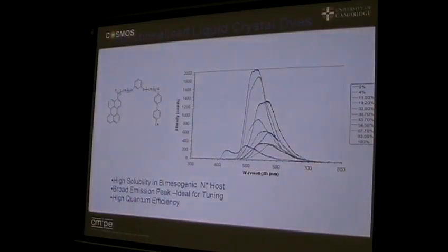One of the ways in which we improve these systems and improve the dyes is, as I said at the very beginning, that you need a high order parameter in the dye. Just to give you a feel for what we do, we actually make bimesogens. We try and bend the cores up a little bit, and then put a fluorophore, a lasing dye, at the other end of the molecule. So I can put different end groups and get much higher order parameters, and therefore much higher efficiencies.